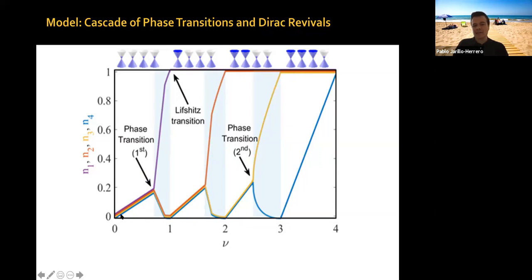As you start adding charge to the system, all of these four flavors are being filled at the same time. You are putting a few electrons from charge neutrality into each of these flavors, each of these Dirac cones, all four being filled at the same time, at the same rate, slowly up. Now, when you are close to having each of these flavors one quarter filled, remember, four electrons fill completely those Dirac cones, so when you're close to filling one quarter each, which means total filling factor one, the system suddenly undergoes a phase transition. It decides it is advantageous to break the symmetry between these four flavors and just fill one flavor completely and empty all other three flavors.